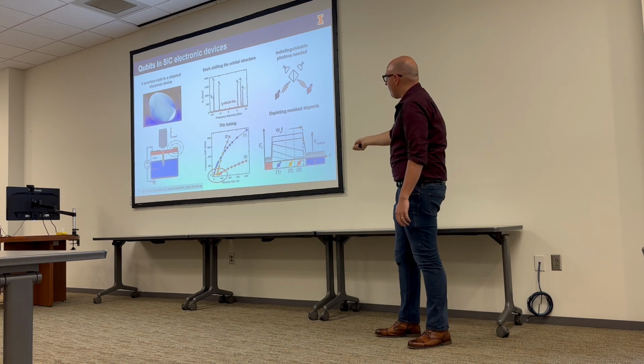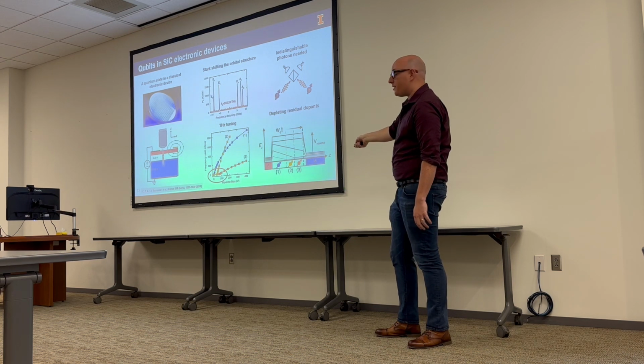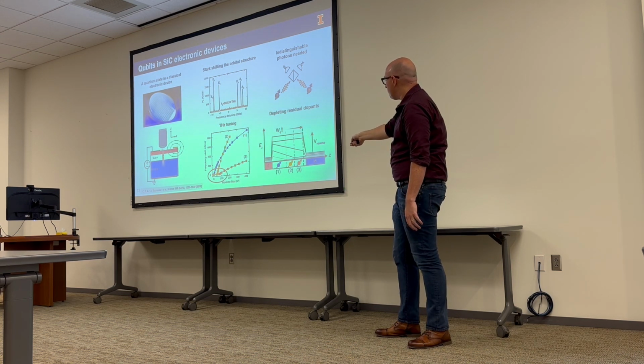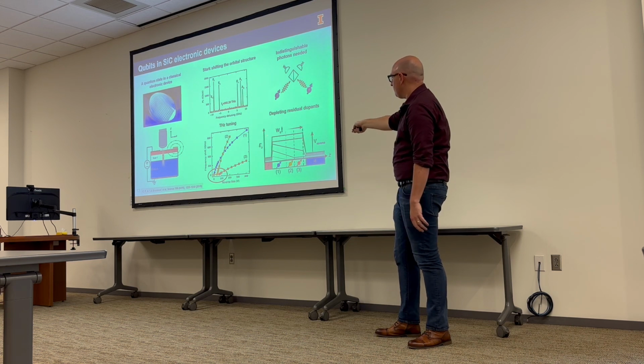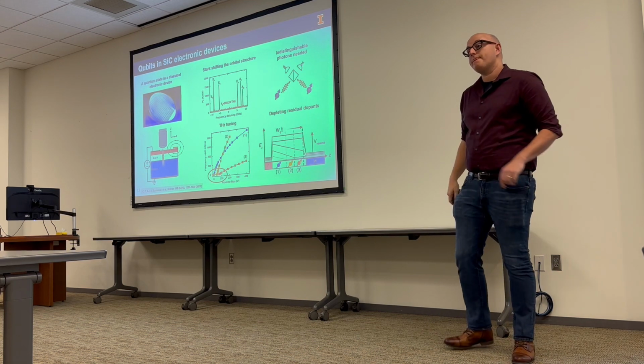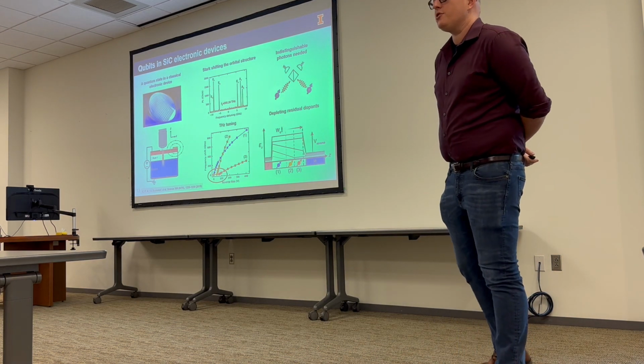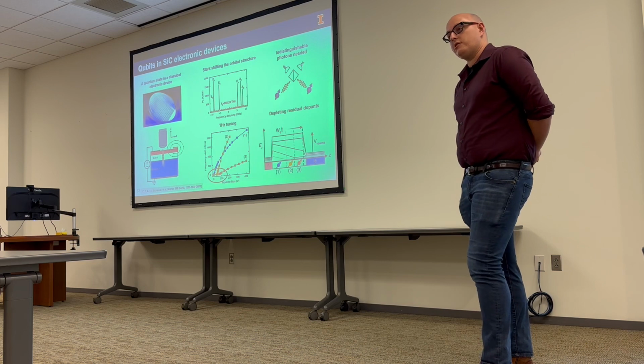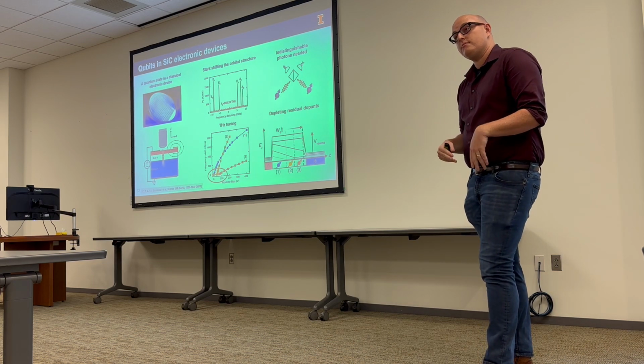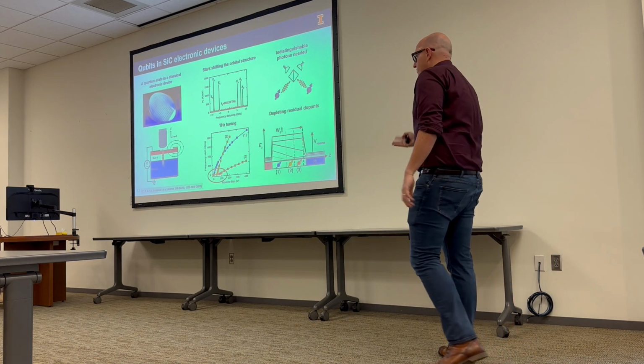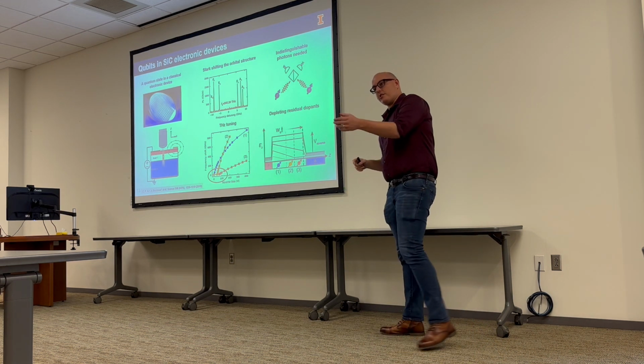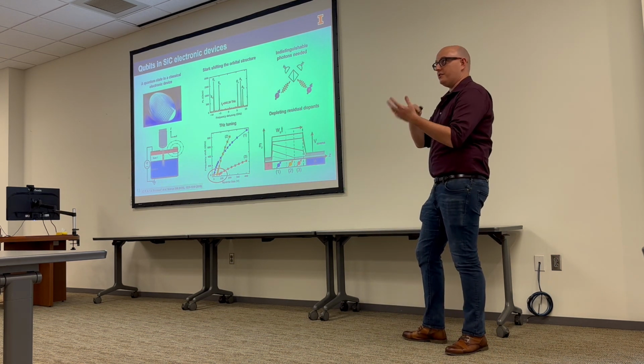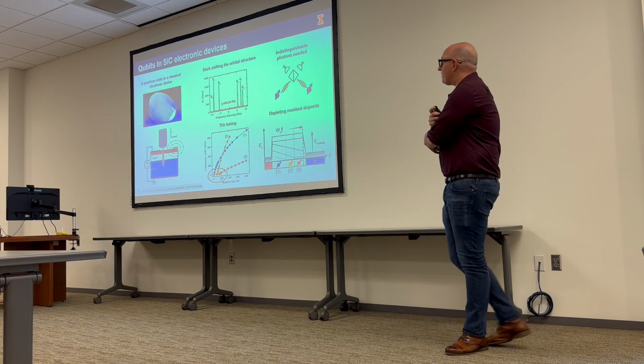And the problem is this is so n-type doped, or sort of unwanted n-type doping, that this field region only penetrates partially through our intrinsic region, and only by applying larger and larger reverse bias does this triangle grow and go deeper and deeper into the crystal until it finally drops uniformly. Can you compensate that charge? Yes. So in higher quality materials, they introduce vacancies to sort of suck up those charges. So it just turns out that this material is a little bit doped, right? Sure, yeah. This is N, but you effectively slightly p-type it, yeah.